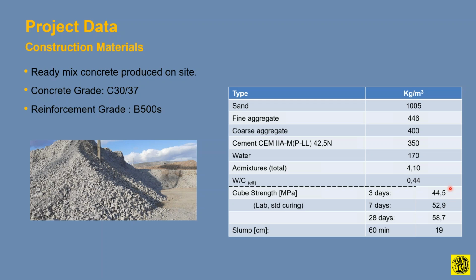So practically the mixed design was C30, as I said. It gave at 3 days 45 megapascal cube compression strength, and then at 7 days 53, and then at 28 days 59 megapascals cube. These are lab standardized tests, so that was the preliminary mixed design, of course. And then we can see here the typical ballast.